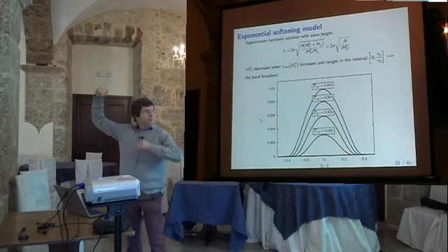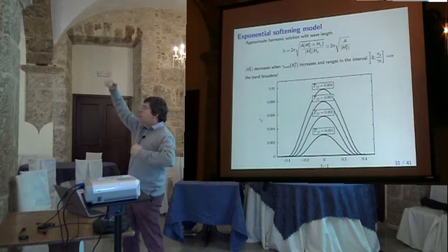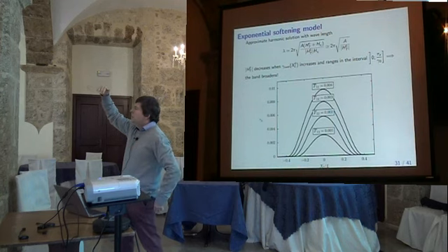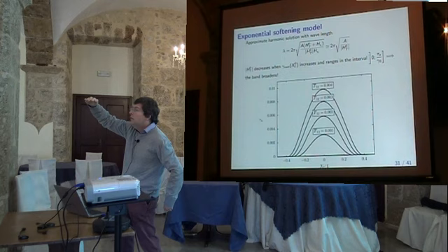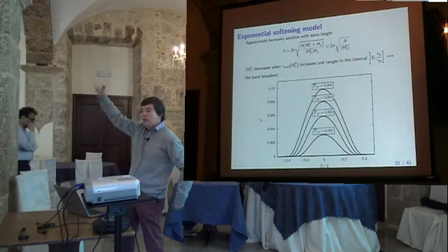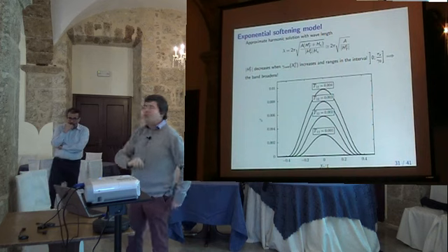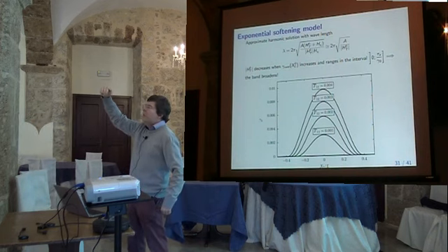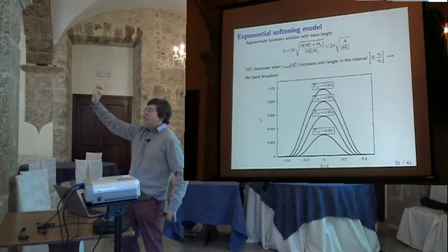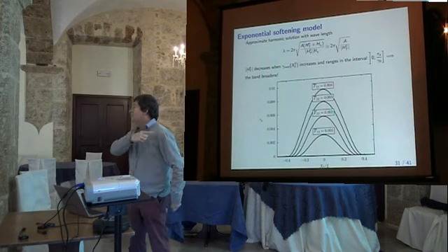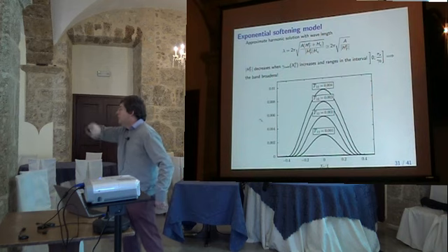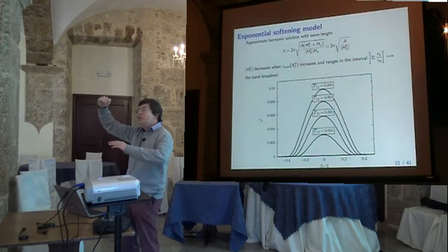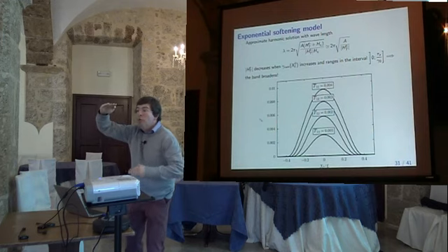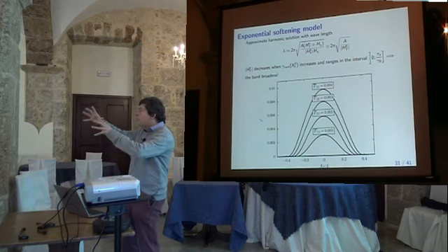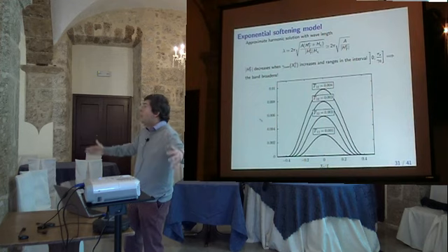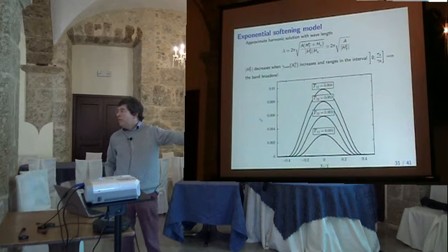The result is that, in fact, what happens is that you have the decrease of the tangent modulus. At the beginning it's negative and then goes to 0 because it's an exponential function, the hardening. So the approximate solution we have worked out is simply that you take at a given plastic strain the tangent and you solve in the same way as for a negative modulus. It gives a cosine and you have the shape, but of course the shape will change and you will in fact go to 0 modulus. So you will switch from the cosine solution moving towards the parabolic solution. And this is what you see in the picture.